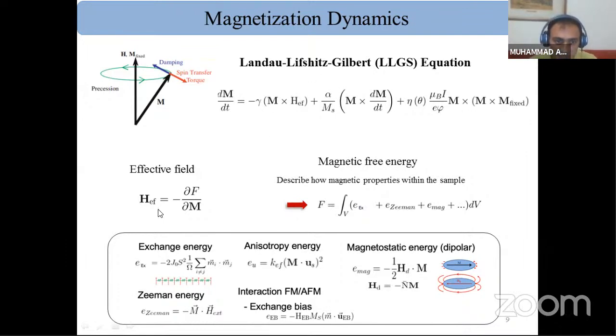Here, the effective field can be obtained from the first derivative of the free energy, and we know that the magnetic free energies in a magnetic system can be exchange energy, Zeeman energy, anisotropy energy, and magnetostatic energy. The exchange energy arises due to the interaction between the spins of the magnetic system, while the anisotropic energy is related to spin orbit coupling, while magnetostatic energy is due to the poles of the magnet. Zeeman energy arises due to the externally applied magnetic field, and the exchange bias is due to the interaction of a ferromagnet with an anti-ferromagnet.